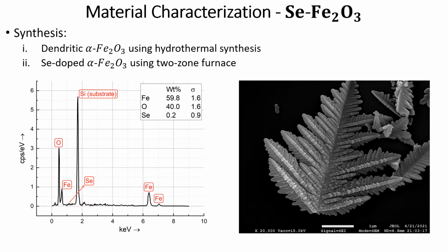We can observe the EDS of the material placed on a silicon substrate. As expected, the silicon corresponds to the highest peak as the material is placed on a silicon wafer. We can also observe that the selenium peak is relatively low compared to the other materials present. It is because the selenium is used as a doping material for this composite.